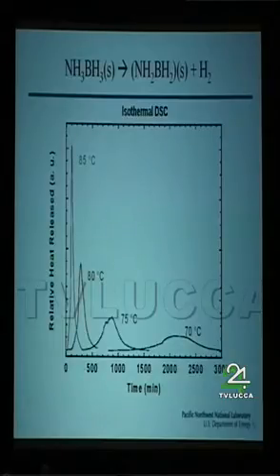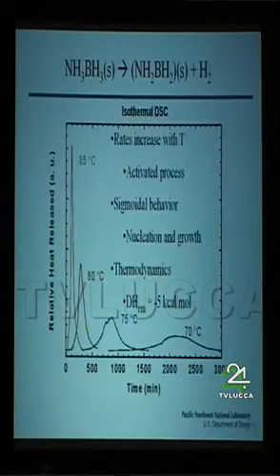When you have something that looks like this, this is sigmoidal kinetics. It's not a simple first or second order process like you see in solution. In sigmoidal kinetics, they tell me, from people who are studying crystallization, there are two steps to this. There's some sort of nucleation that happens to start the reaction, and then once that happens, it takes off and releases the hydrogen until about half of it's gone, and then it can't overlap anymore. So this rate increases with temperature. It's got this sigmoidal behavior, so it's indicative of some sort of nucleation and growth process for formation of hydrogen. In the thermodynamics, just to make sure we're on the same page, it's 21 kilojoules exothermic, 5 kcals.